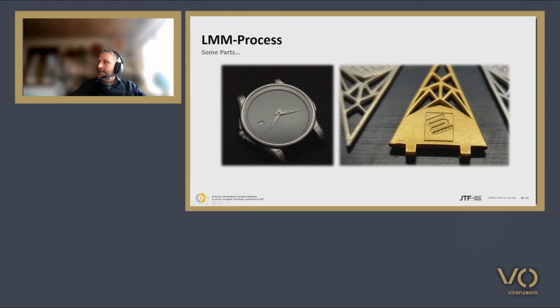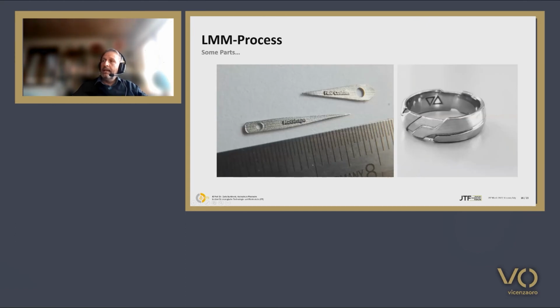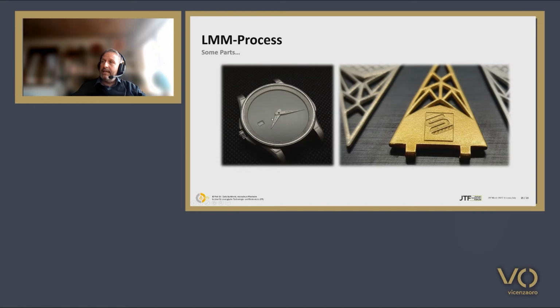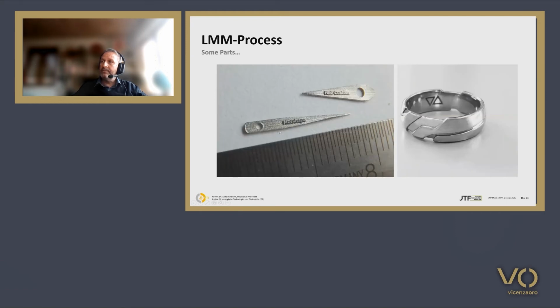Yeah, and you see here on the surface, this is not treated at all. You see the kind of pixel structures. In this watch, the indicators here are also printed in 3D, and this is one centimeter here just to give you an idea of how small these parts are. You see the printing lines, yes, but you also can read what is on the surface of it. On the right side, you see a ring, as printed, only tumble polished.